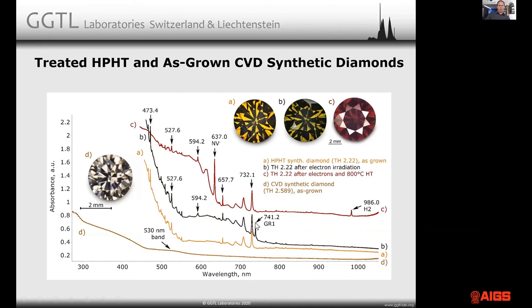After irradiation, you simply overlay a GR1 band on top of the absorption, and in consequence, you have dark yellow plus green. Well, that gives basically some sort of a brown. Now, just for the fun of it, we heat treated the stone afterwards at 800 degrees. At 800 degrees, GR1 disappears, and you're creating strong NV centers at 637 nanometers. And the broad band that results from this is the reason why your stone after treatment appears brown-red instead of olive brown. So these are the samples that you can get in synthetics.